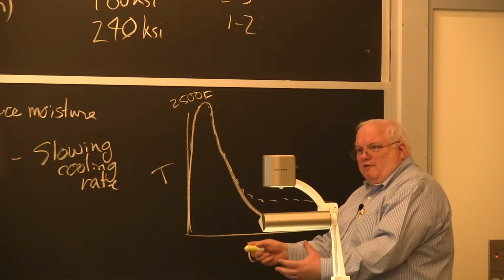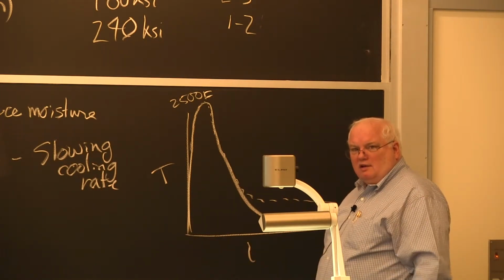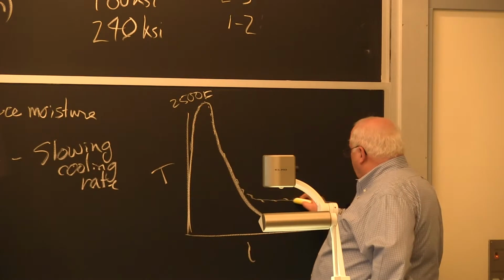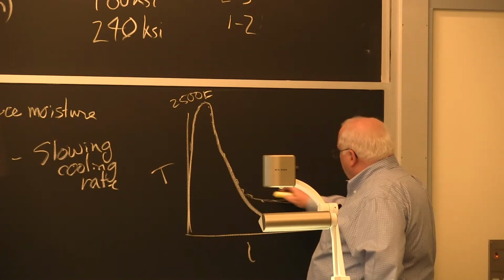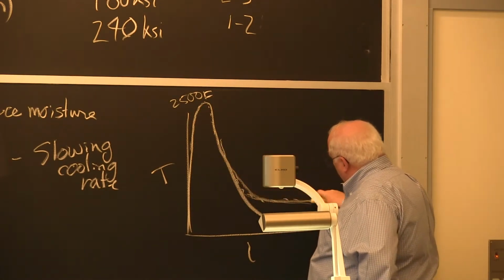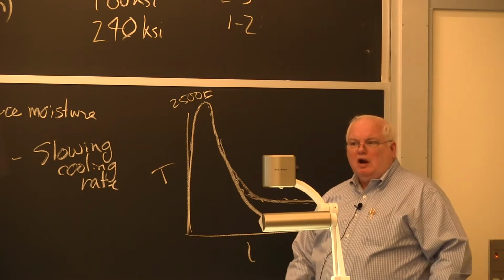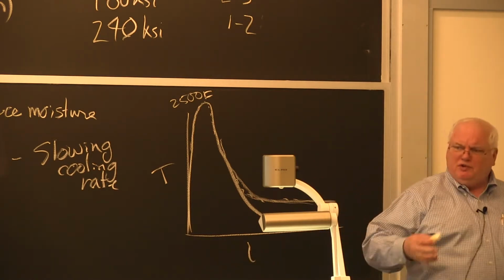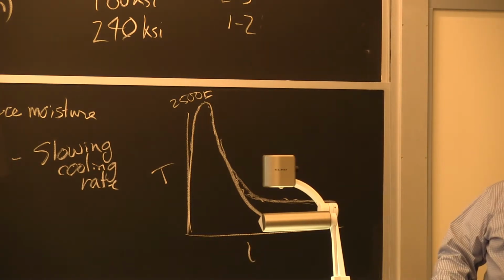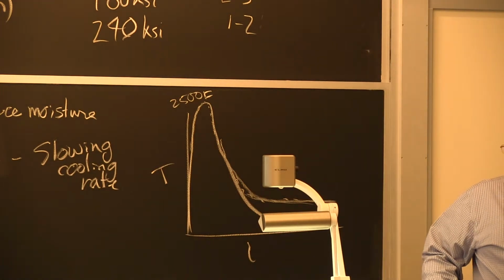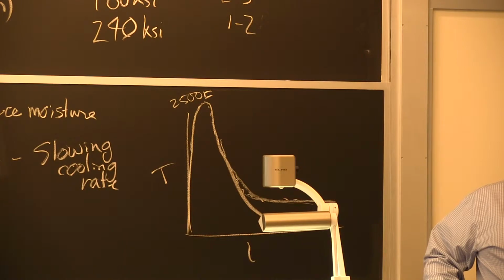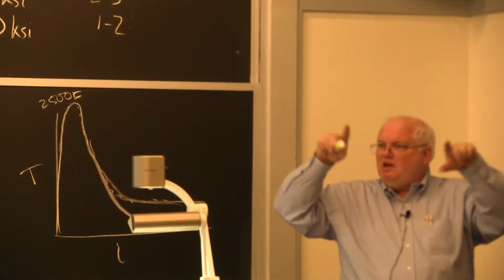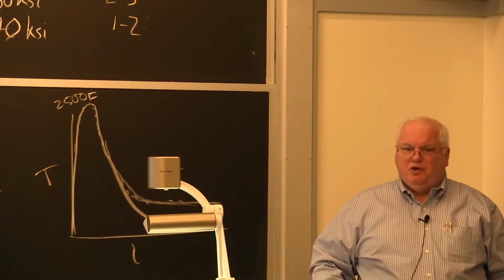Remember, 25 degrees is the worst temperature I can be at. If I heat it up to 100 degrees or 200 degrees, it will cool down, but it will cool down to a higher temperature, and it will stay at that temperature for this great big piece of steel that weighs several tons for an hour or two. And that allows the hydrogen to diffuse out. I'm taking care of that. I'm taking advantage of that little V-shaped curve I showed you.